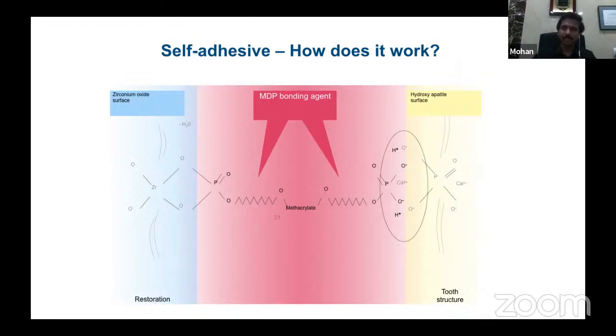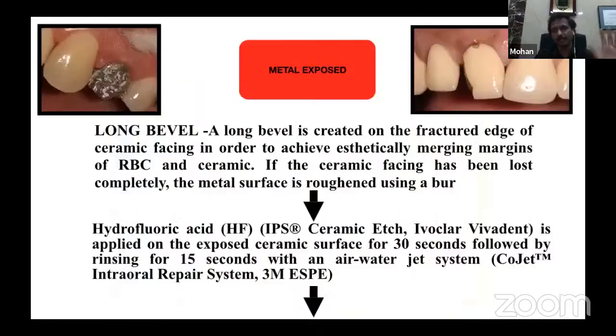Now coming on to the reason why they are very, very successful is one magic resin which we call in dentistry MDP, 10-methacryloyloxydecyl dihydrogen phosphate, which is like a quick fix. It's a magic resin. It could stick to anything. So the addition of MDP made the whole difference in the success rate of the repair work we do. Generally I'm talking about a metal ceramic. The same rule applies for all-ceramic also, but the only thing is that I would not be using any opaquing agents to mask the metal surface which is exposed.